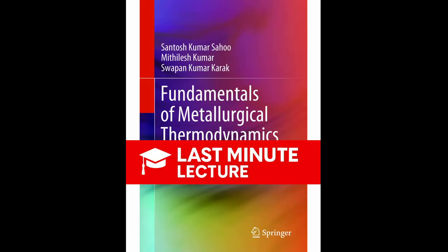However, the most practical form of this is for vaporization or sublimation, where a liquid or solid turns into a gas. Here, the approximations are significant and valid. First, we assume the volume of the resulting vapor is huge compared to the volume of the original liquid or solid, so delta V is approximately just V vapor. Second, we assume the vapor behaves as an ideal gas, so V vapor equals RT over P. You make those substitutions, integrate, and assume the heat of vaporization is constant over a short range, and you get the integrated form, equation 4.100.